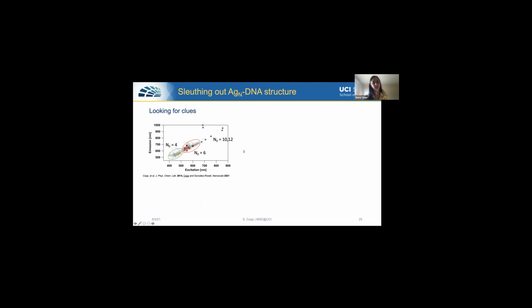So we investigated this and found that this abundance of data points here corresponds to clusters with four neutral silver atoms. This corresponds to six neutral silver atoms. And then these, which I don't have data for on this plot here, have higher numbers of neutral silver atoms. These are the so-called magic numbers of these clusters, meaning that certain numbers of electrons result in filled electronic shells. If the clusters were spheres, we would expect them to have magic numbers 2, 8, and 20, and so forth. This is somewhat similar, but not exactly the same as the atomic numbers for the noble gases, by the way.